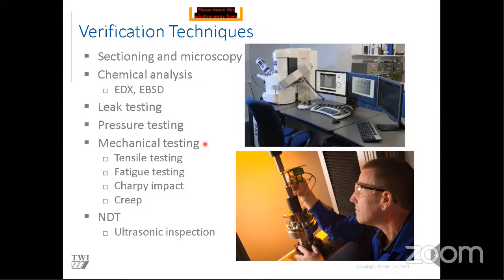But the problem with that is it's not a mechanical test. So we do a load of different mechanical testing, ranging from tensile through to fatigue. If you look at Charpy impact, we don't often do that on the bond itself, because trying to target the bond is almost impossible. I'm talking more about Charpy testing of the parent material.